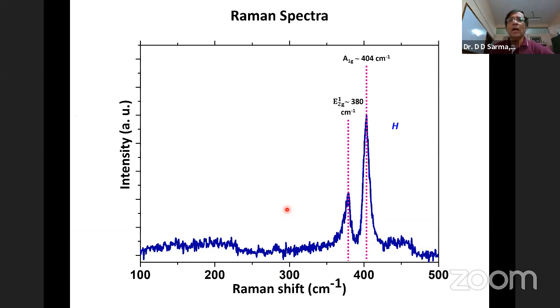I've told you that if I look at the H phase, the stable phase, I see the Raman spectrum, these two. The way it is done, we intercalate lithium, we ultrasonicate, exfoliate it, and then we wash and get rid of the lithium. What Devashmita said was, let's not try to get rid of all the lithium, because we want to understand what lithium is doing. Let us get rid of lithium in steps. So she looked at the system without washing, then washing with water once, twice, thrice, four times, up to 12 times, 16 times. I'm going to show you the results of zero wash, that will be called 0W everywhere, and 12 wash, because of that contrast.